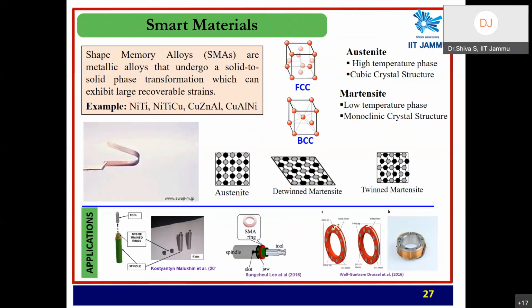So this is one such work which I would like to show. This is the shape memory alloy based work which I carried out as part of my research. It is a functional material which is widely used for functional applications. You can see the actuation on the application of heat. The material remembers its shape and just returns to it. For bulk applications, you can also use shape memory alloys for smart tool holders, where you apply heat and it starts to clamp the tool even more tightly. As an effect of clamping the tool much more tightly, we find that there is less vibration, and the heat generation at the tip of the tool due to vibration can be substantially reduced, and the life of the tool can be increased.